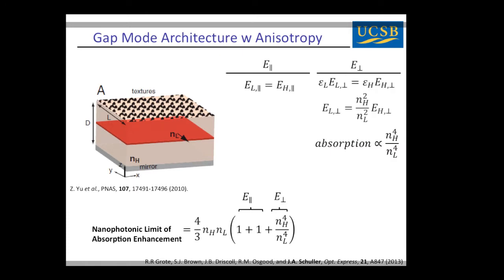And really what's coming into play here is something very fundamental. So I'll just explain that and then wrap up. So what's the fundamental difference? The parallel component of the E field is always continuous across an interface. The perpendicular component, it's the displacement field that's continuous. Okay? So because of this, let's take this dielectric gap mode, we can have an enhancement of the perpendicular field component that scales like the ratio of refractive indices squared. And that's just the field, so the absorption scales like the fourth power here.